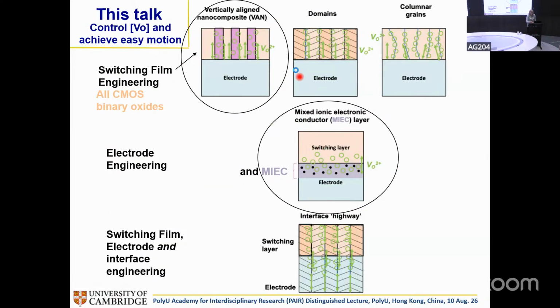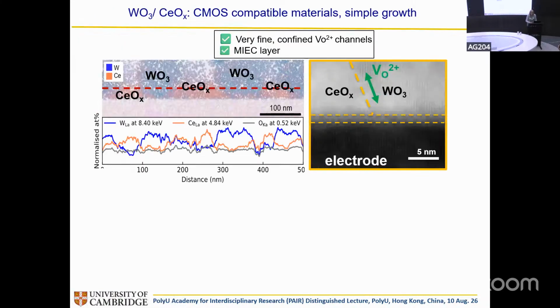So now we've gone through this high temperature grown material. We showed that we can get control of the vacancy channels and uniformity. Now we want to say, well, actually, those are high temperature grown. We can reduce the temperature a bit, and we can choose materials which are more simple. So we now want all CMOS compatible materials, which those weren't before. We want binary oxides, and we want to try to lower the temperature a bit. Furthermore, we also want to think about what happens when you move the oxygen down, and where does it go? It will be trapped at the interface unless you can move it down into the electrode. So here we want to add in this mixed ionic electronic reservoir layer where we can have the vacancies going in and out and also conducting. So that's what I'm going to show you next as an example.